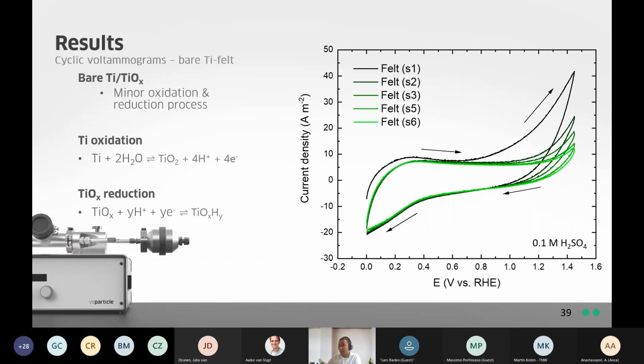The performance of these materials was studied using cyclic voltammetry. Here I show you the CV plot of just the bare titanium felt. As we sweep from lower to higher voltages, we get some minor oxidation steps. And this is just the oxidation of titanium to titania. And as we sweep to lower voltages, we see minor reduction steps, which are the reduction of your titanium oxide to a titanium suboxide.